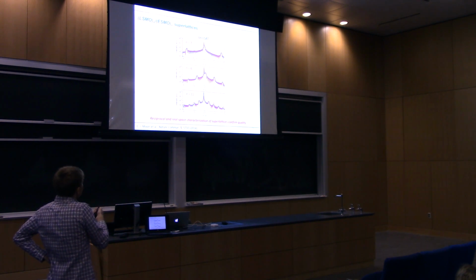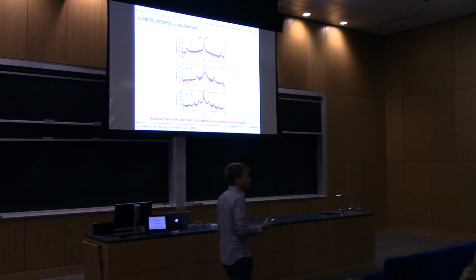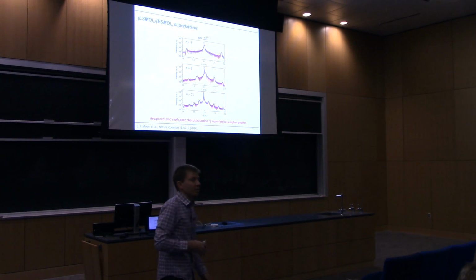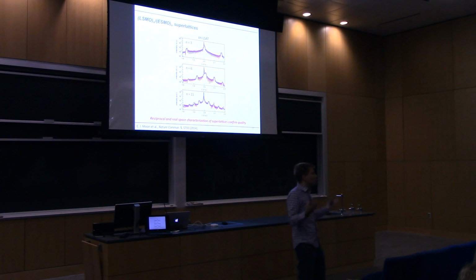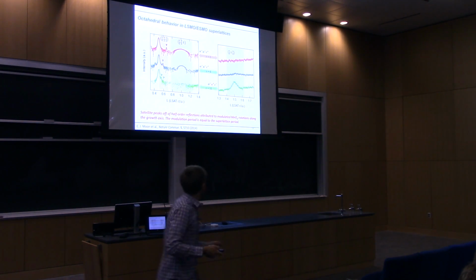If you would rather see this in reciprocal space, here's the diffraction data. These are L scans of the 3-3, 6-6, and 11-11 superlattice. In simulations, just assuming everything is absolutely perfect with perfect interfaces, it's kind of remarkable how well the simulations actually match the data. So I hope to convince you that we have nice superlattices, that these aren't just random outliers. All right, now moving on.